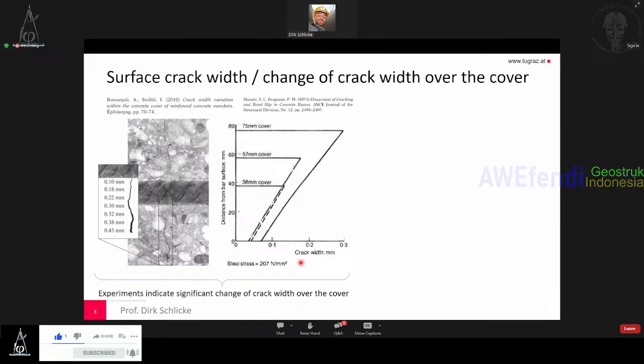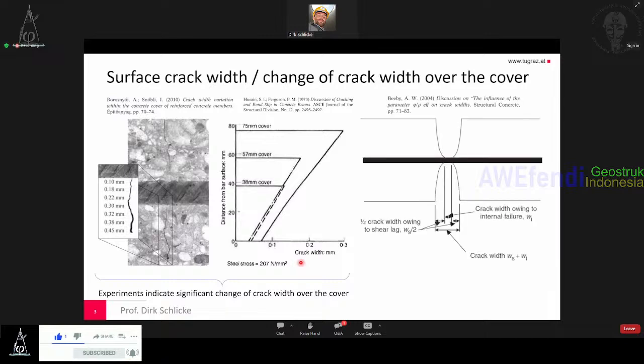These experiments indicate a significant change of crack width over the cover, obviously. There's another contribution from Professor Beeby from the UK in the discussion of the influence of the parameter diameter versus effective reinforcement ratio on crack width. And there he gave us this scheme where he showed a bar, there's a crack, and you see here some crack deformation over the height.